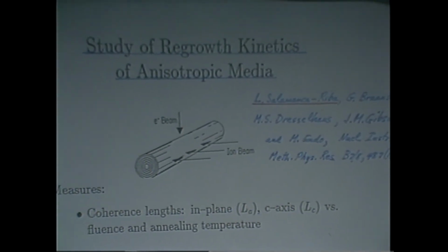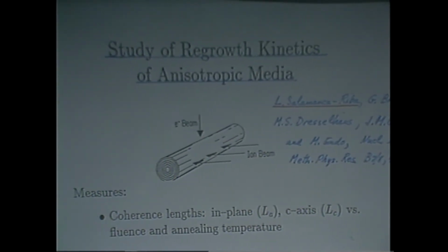So what we did, this is the sort of thing that you can do, this is engineering, but it has quite a bit of science in it. So here's a carbon fiber, about 10 microns. And if you implant it with something, then you can make this side implanted, so disordered, and the back side where the implant didn't go is ordered. So we always have a comparison on the same fiber.